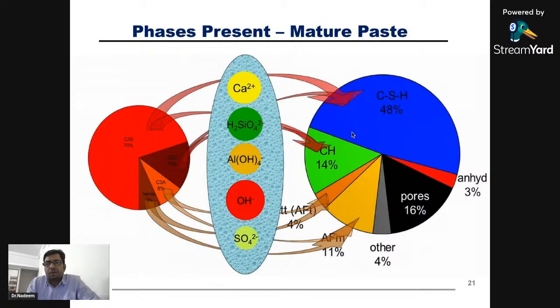The majority compound is calcium silicate hydrate gel, 48%, which is the compound that actually imparts the strength to the structure. Then these are the anhydrous or unreacted products. These are the pores we just observed, because of evaporation of the water, internally a lot of pores are being created. These are the other compounds. Here is the calcium hydroxide. This is ettringite. This is a calcium aluminate monosulfate phase. So these are the various phases being created out of these four major compounds.